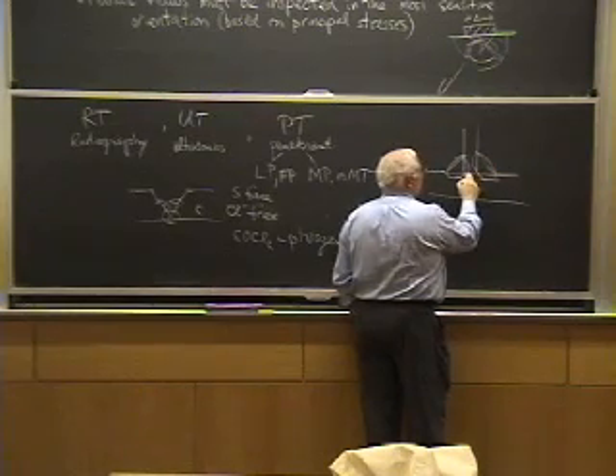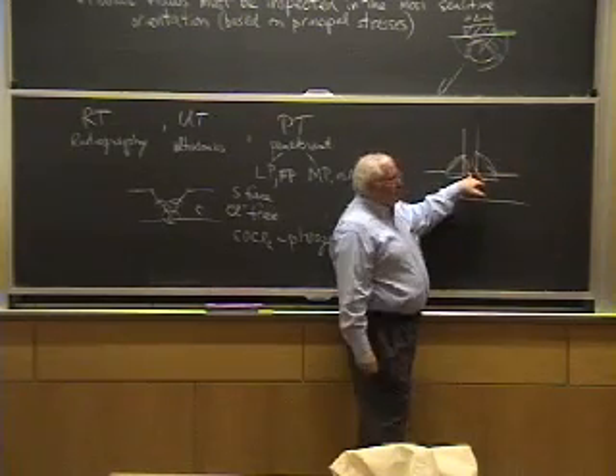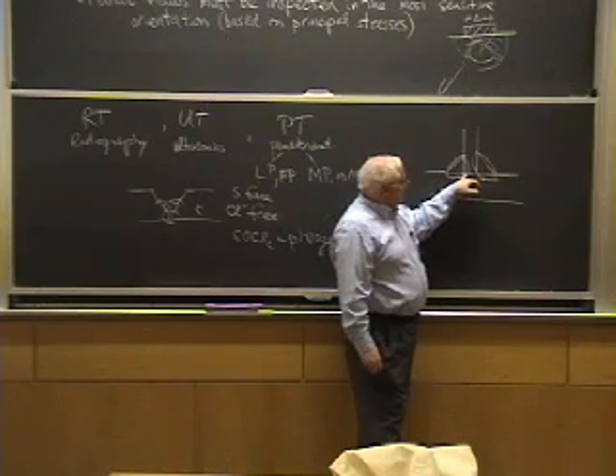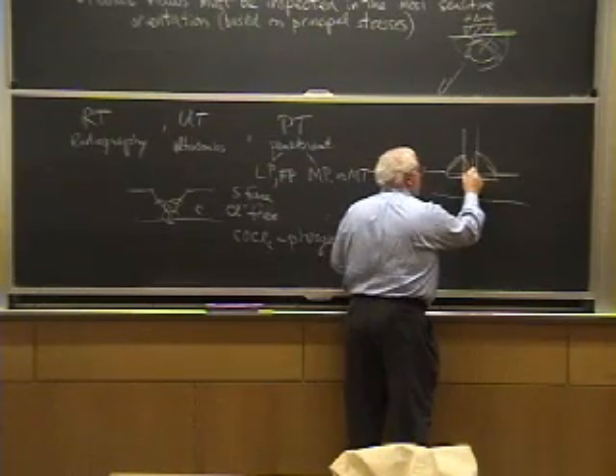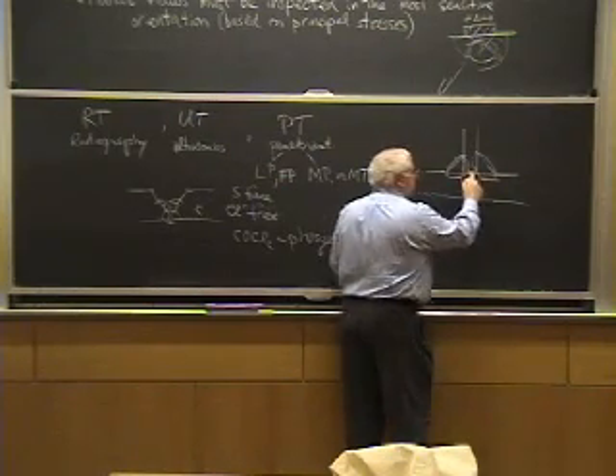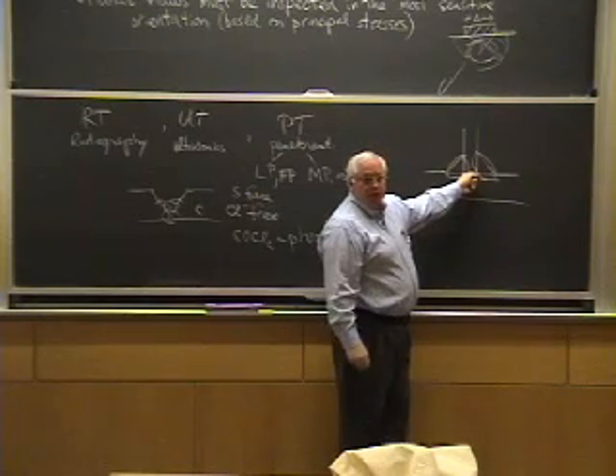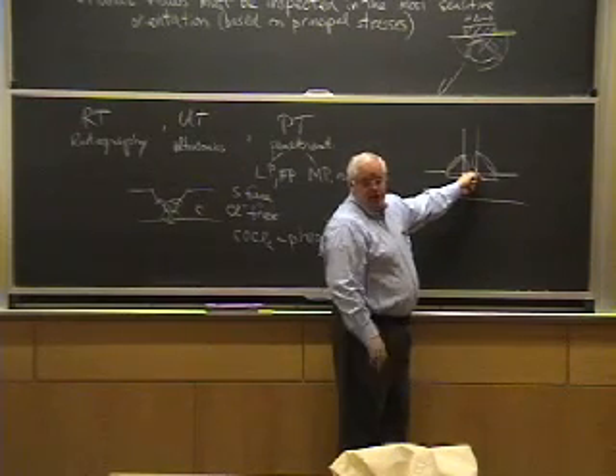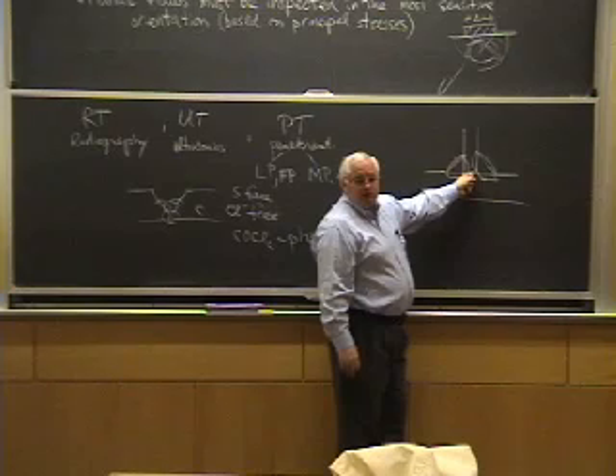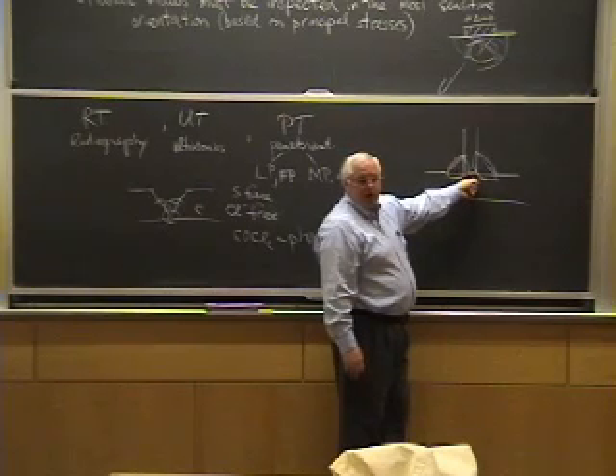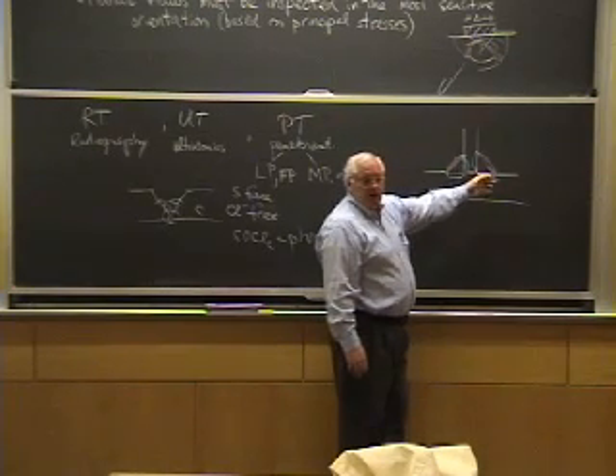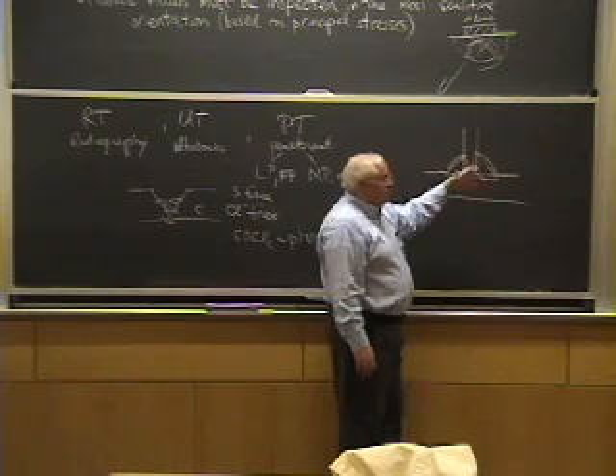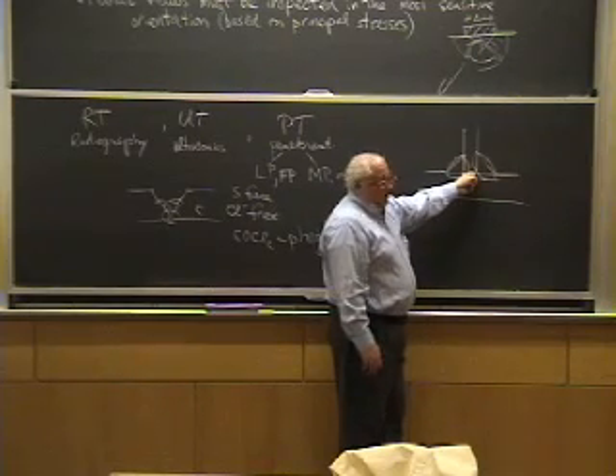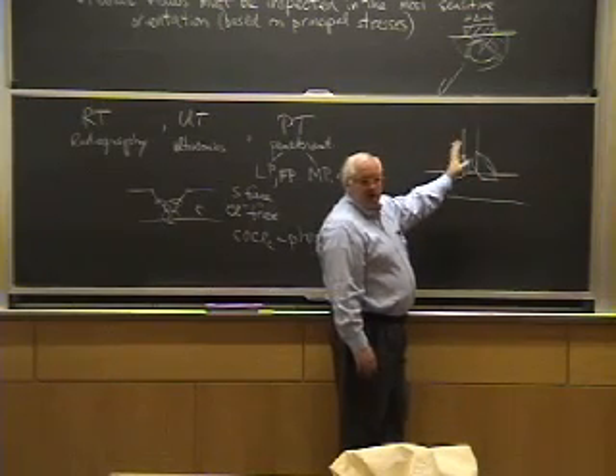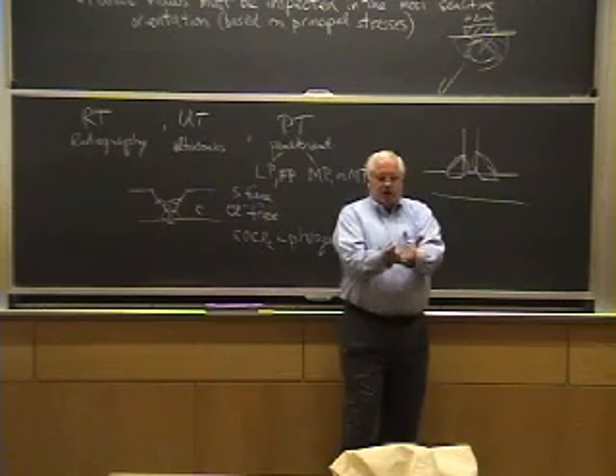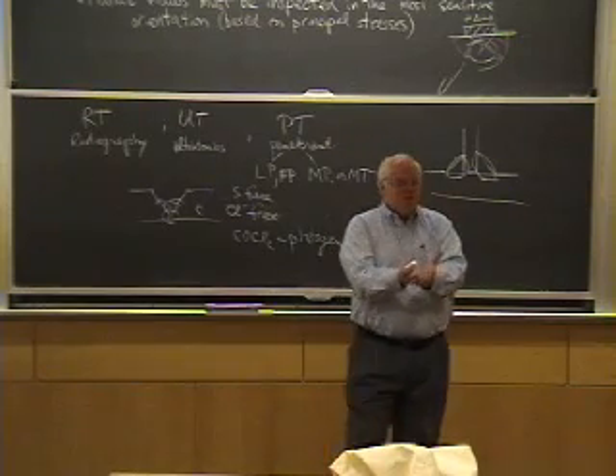Typically, you sometimes have what they call full penetration fillet welds, but in other cases, you actually have a notch right there in the center where you never welded the material. If you have a fatigue situation, that is a stress concentrator, and you might end up with a fatigue crack growing from inside out. But if you don't have a fatigue situation, it's just a simple building, you don't need a full penetration weld. This is a very simple weld to make because the welder has to lay his metal down in a V groove, basically.